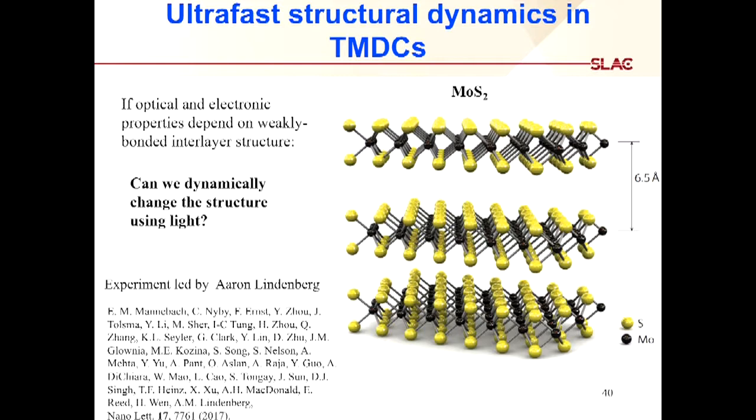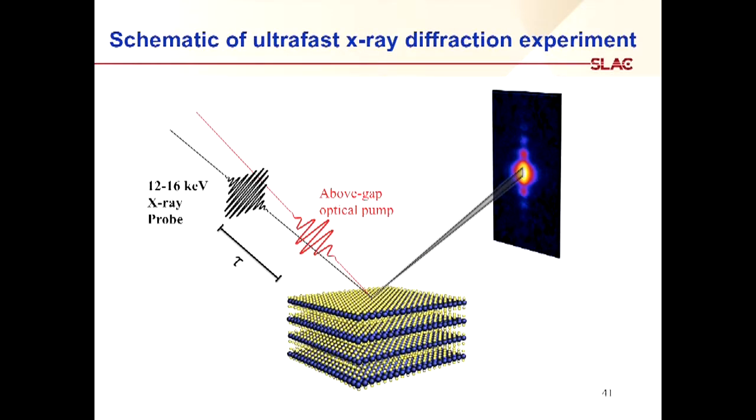So this experiment was led by Aaron Lindenberg here at SLAC in Stanford and involved a big team of people, as you can see. And the key measurements were carried out just down the road at LCLS. Okay, so what was the experiment like in this case? We got a multi-layered sample of moly disulfide like this, with these in the basal plane here. And then we excited with an above band gap ultra-short optical pulse. And we probed using X-rays in the structural regime where we could see a diffraction pattern. So this was a good experiment for somebody who was basically an optical spectroscopist because it was a pretty simple experiment. We essentially got the information by looking at a specular Bragg reflection here